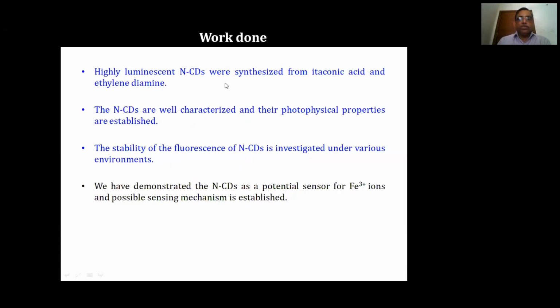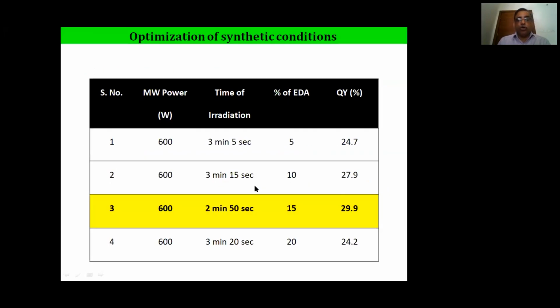Highly luminescent CDs were obtained from this, and we have nicely characterized these CDs. Stability of the fluorescence of these NCDs was investigated, and we also demonstrated that this material can work as a good sensor for the Fe3+ ion.